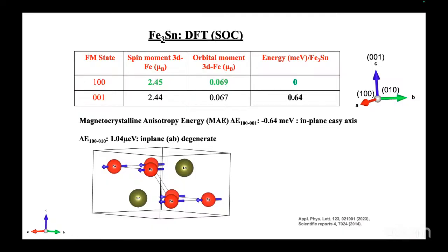I don't think it will change much with the inclusion of correlations, I suspect. But for DFT plus U, if we take the double counting to be in the more localized limit, we get an increase in the band splitting because the bands become more localized. So there we get a reverse effect, that the J_ij strength increases. But the mechanism behind these exchange interactions can vary from system to system, depending on how they are mediated. It can be double exchange or superexchange, which can differ in these methodologies.